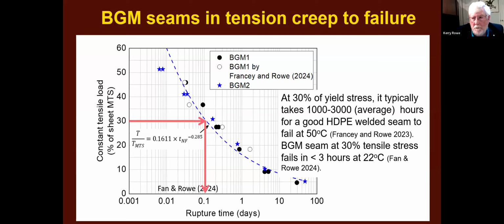So we're doing the same procedure, it's just on a weld, not the sheet, that we do for a stress crack test, but without any notching. And this compares with about 3 hours at room temperature for the BGM. Quite a difference between 3 and 1,000, let alone 3,000. Now, if you go to a lower stress, as you might expect, it takes longer, but not all that much longer. So if we go to 10%, it's about 128 hours.